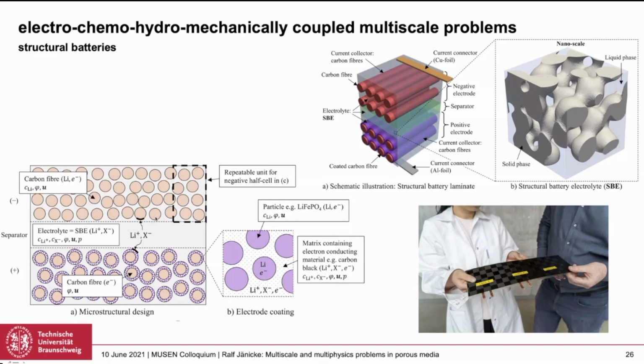And the funny idea that's built in, and just to give you an idea why this is a porous medium, and just look how the separator looks. That's a polymer, which is not active electrochemically, but it's filled with a liquid electrolyte, where the lithium diffusion takes place, or lithium migration takes place. On top of that, this structure is deformable, so there might be something that we call convection, so a motion related to the deformation of the pore scale. And here, just to show that this is not only dreamt up, they can even produce it, so it's somehow working. But for us, it's of course a very, very fancy application to test our numerical and modeling tools.